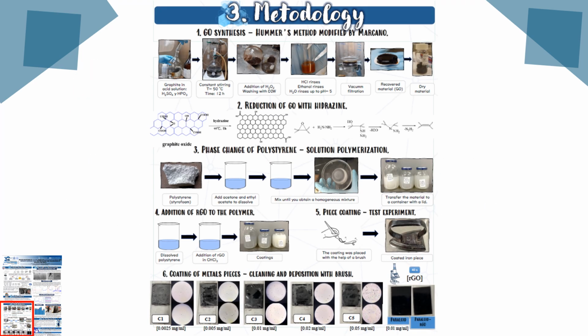The method mainly involves synthesizing graphene oxide using the Marcano-modified Hummers' method. This means putting graphite in an acidic solution to add oxygen groups to the graphene sheets with an oxidizing agent, potassium permanganate. After several washes to reach a pH of 5, the material is dried and we end up with graphene oxide, GO.